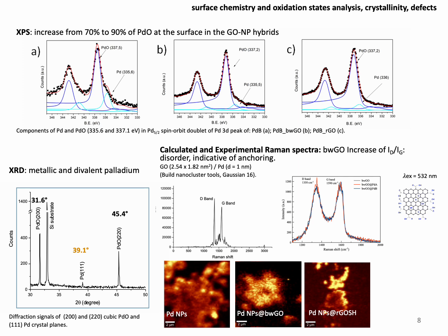The Raman and the 2D mapping identify palladium nanoparticles as the bright spots, due to the electronic structure and the plasmonic properties, and the graphene oxide sheets as the brown region. All the samples show the characteristic D band at 1340 inverse centimeters and the G band at 1580 inverse centimeters, with no observed peak shift. Instead, what is changing is the integrated intensity ratio between the peaks of the disorder to the order, which points to a more disordered structure in the presence of the palladium nanoparticles, confirming the linking, the anchoring of the particles.